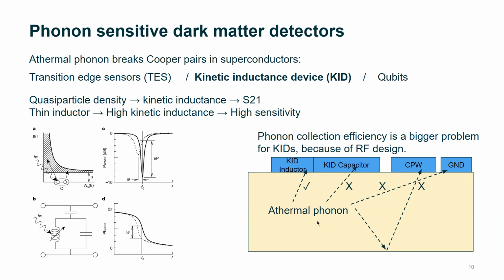But if you consider how the phonons propagate, they actually bounce around multiple times before they reach your superconducting films. And because this is an RF circuit, you not only have the inductor, you also need to build the capacitors. Usually the capacitor takes up much more space than the inductor. You also need your RF feed line, and to ensure good RF properties, you usually have a full ground plane on the chip. So everything else can absorb phonons as well, and it's not active, so your phonons will get lost. Only the phonons hitting the small inductor can generate the signal. This is a big problem in the KID application.